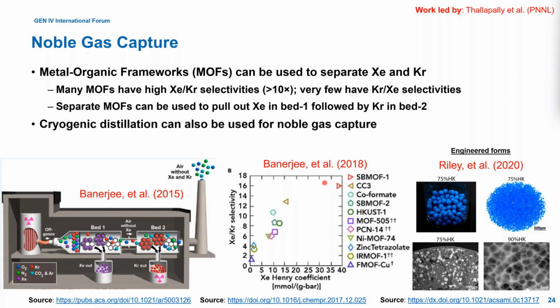And there are very, very few, but he has found one krypton selective MOF. And so one of the thoughts here is that a two-bed approach could be used where MOF 1 is used to pull xenon out of the gas stream, and then MOF 2 is used to pull krypton out. One of the issues with MOFs is that they are made in a very fine crystalline, I would say, fine particle size.